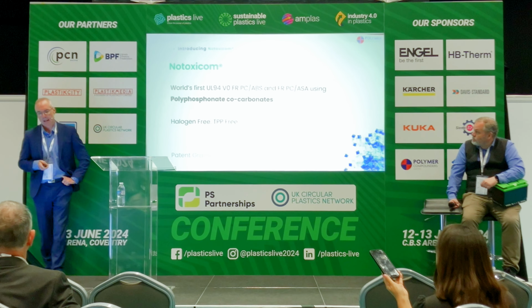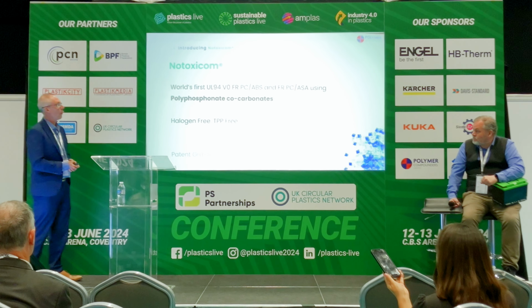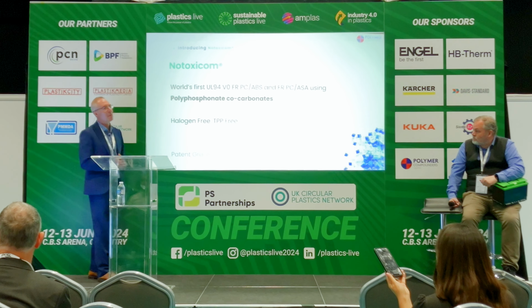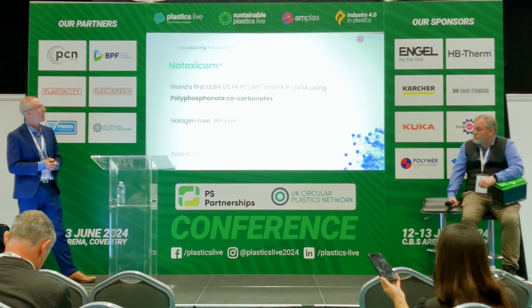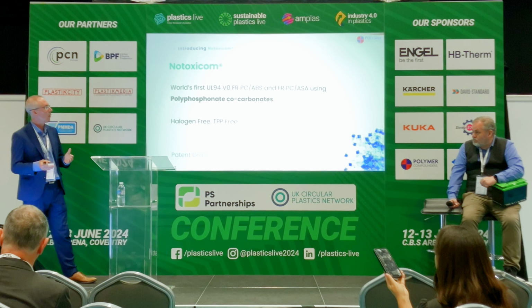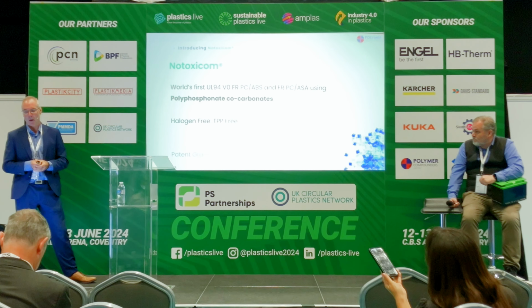So we've been playing with a new breed of materials, technically not actually a flame retardant additive, but a highly flame retardant polymer system. These polyphosphonate co-carbonates have extremely good flame retardancy, with absolute minimum toxicity and impact on human health. We found that when we blend this polymeric system with PCABS and PCASA, it can match the current properties of existing flame retardant materials in terms of mechanical impact and flow, but with far less impact on human health. It's halogen-free and triphenyl phosphate-free. We really think this is the future where the industry should be looking.